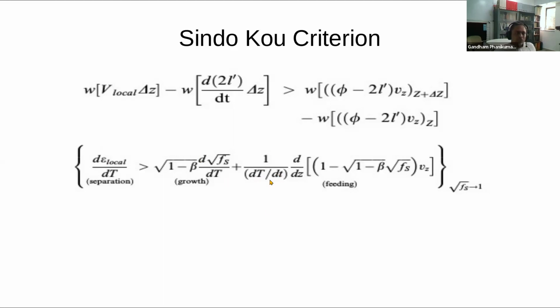Now, this is a very good clue for us, because Kou used only the first term to grade the alloys, and he neglected the second term, which has come from the Rappaz criterion. What we have done is look at the second term also and shown that in situations where there's a cracking possibility because this part is already bad, you can improve here by putting in a slightly higher cooling rate and therefore keep this right-hand side term small, so that you can ensure that the separation doesn't take place. That has been done and we have verified it with some alloys also.